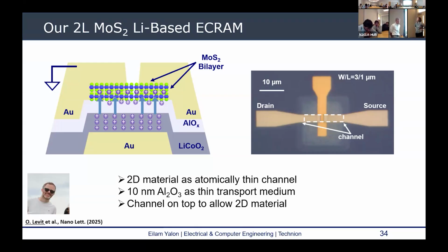Well, the doping effect from the alumina is kind of a background effect, because what we're working with is modulating the conductance. So you would have some background doping from that electrolyte, whether it's alumina or maybe a different oxide. And in terms of the thickness, we validated the thickness when we developed the process, and this is patterned alumina, not ALD. For thinner films, the leakage to the gate was too high. With thicker films, we didn't get much effect from the ionic gating, so that was roughly the optimum that worked.